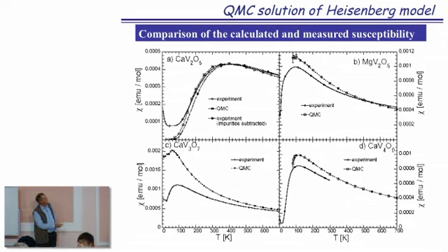And that is the trick where we have experimental curve and calculated theoretical curve. Here, this upturn is due to the impurity, so this one is when impurities are excluded. So you see it's a beautiful agreement, but a beautiful agreement for the case when we have one very strong dimer interaction. When we have frustration, that's typical case of frustration.